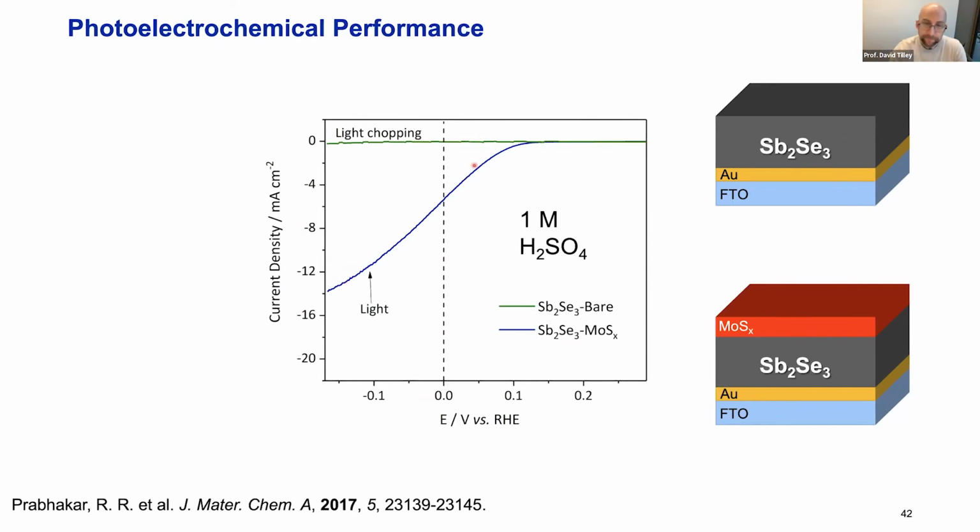which is very exciting. It's also noteworthy that this does not massively corrode. If we were to do the same reaction with copper oxide, we would get a massive corrosion current, and then it would just be totally dead. So it seems to be somewhat robust. So this was good, but we have a very late onset potential. We'd like to push this farther to the right to get more voltage.